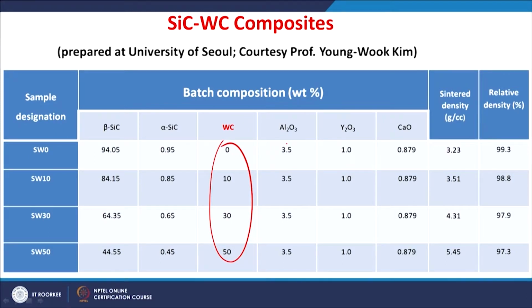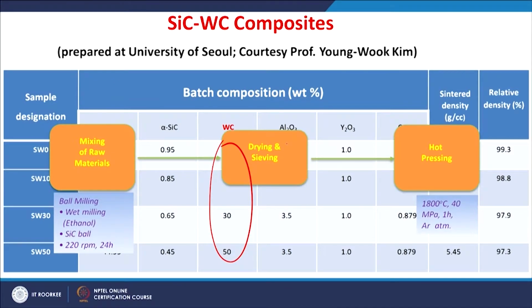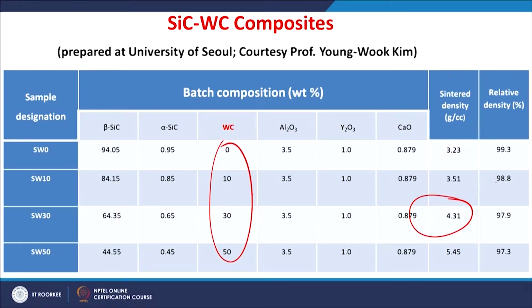These were prepared by hot pressing. Before hot pressing, these batch powders were mixed, then dried and sieved, followed by hot pressing at 1800 Celsius and 40 MPa for 1 hour in argon atmosphere. The sintered density of these materials is 98 to 99%.